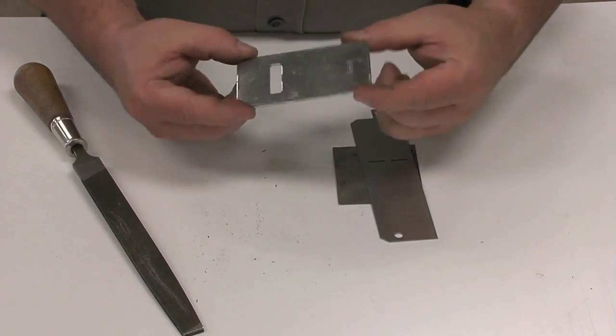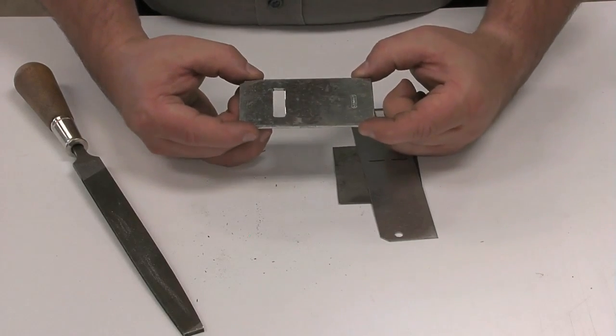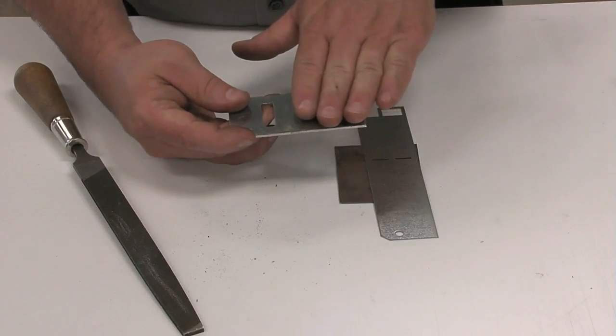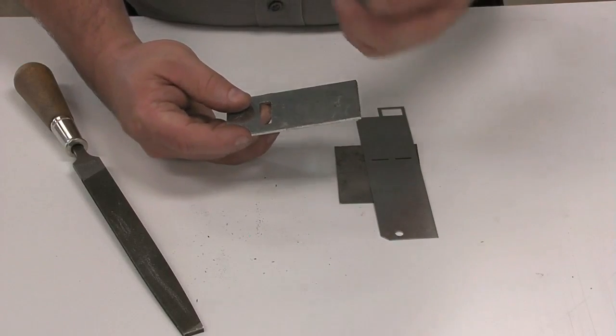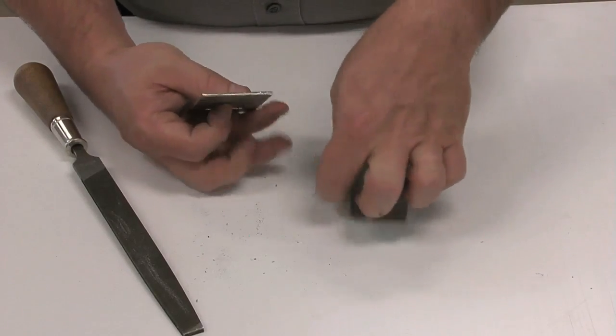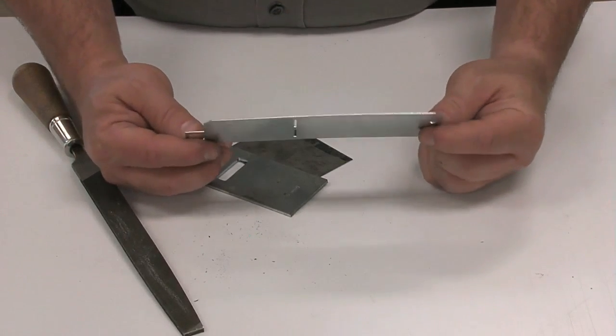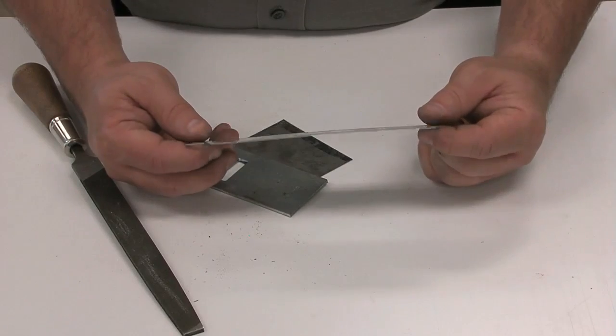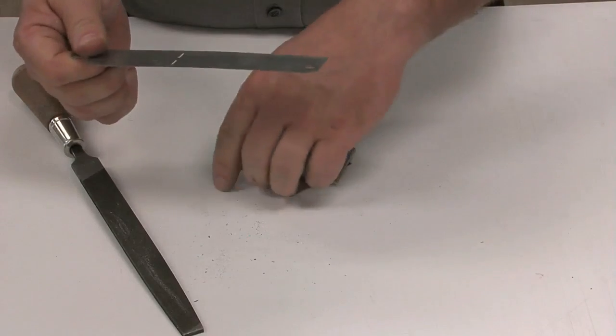The big deal with galvanized metals, we have to be careful because the galvanizing is a zinc coating and zinc is toxic when it's burnt. So anytime we have something that's zinc coated, we never want to weld or solder something like that to it unless we're in an extremely well ventilated area. This is actually a piece from inside of a computer case. That's very common to have galvanized parts in it. Just be very careful anytime you sand or file that you're not inhaling that dust or when you get it hot.